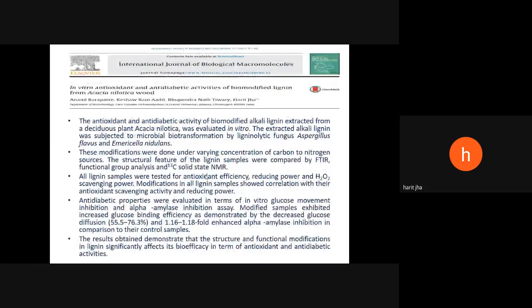Then in this work, we have modified the lignin. This was again published in the International Journal of Biological Macromolecules. In this, we have used the enzymatic system from Aspergillus flavus and Emericella nidulans for modification of the structure. And this structural modification was compared by FTIR and C13 solid state NMR.